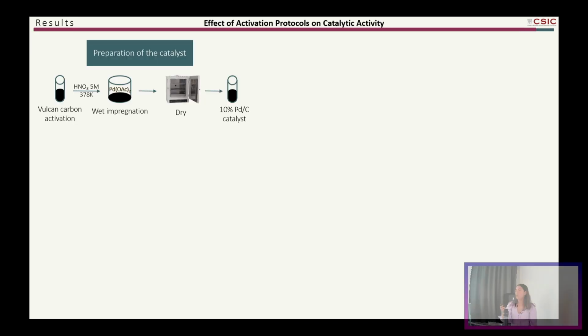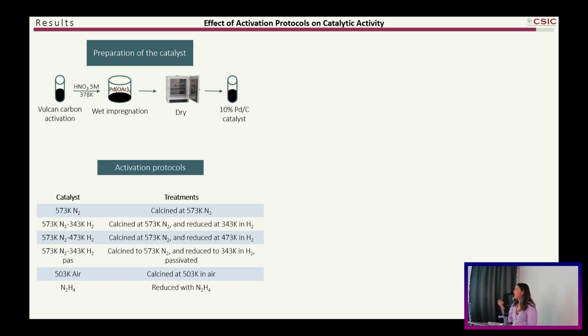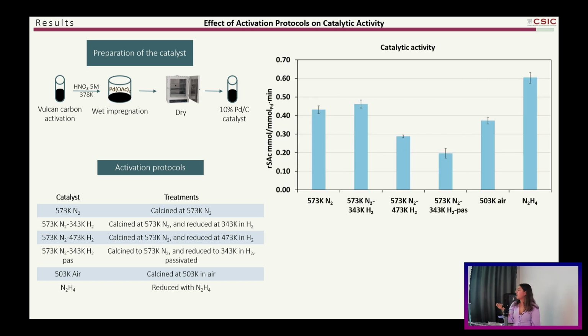So first, we prepare the palladium carbon catalyst by wet impregnation, and then we carry out several activation protocols such as calcine the catalyst in nitrogen, calcine the catalyst in nitrogen and then reduce with hydrogen at 2 different temperatures, or calcine the catalyst in nitrogen, then reduce in hydrogen and finally passivate, or calcine the catalyst in air or reduce with hydrazine. So in this graphic, you can see the succinic acid formation rate, and we can observe